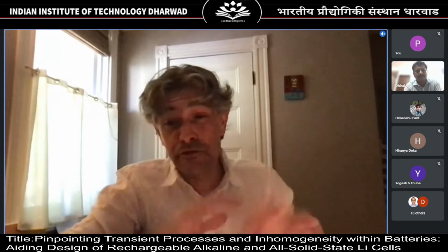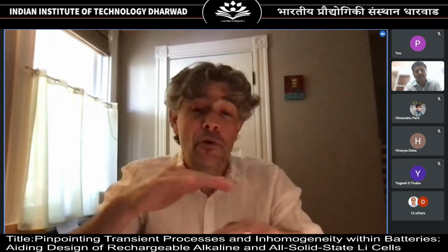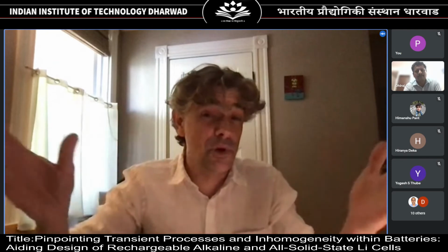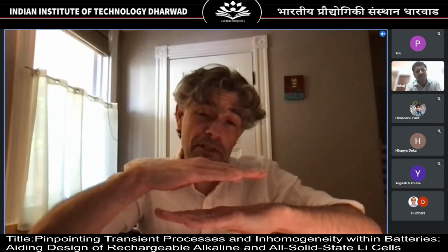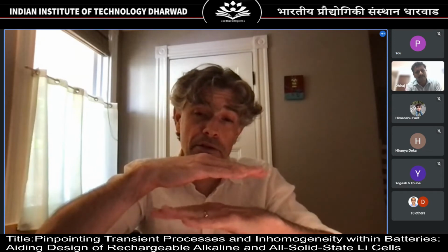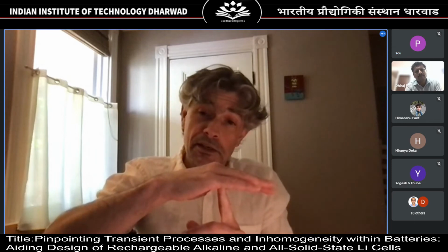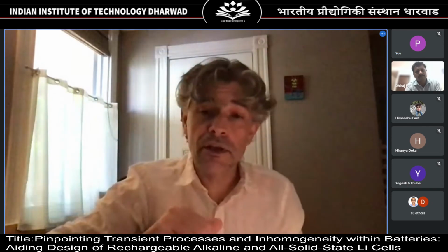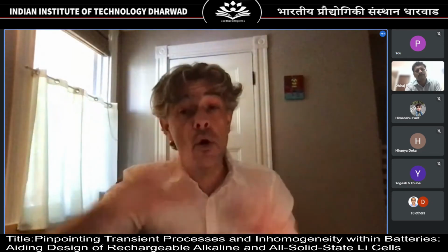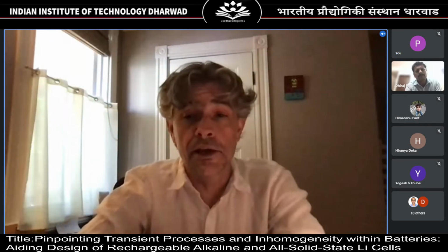Now, the layered form is even different because I showed that it maybe has those pillars in it. So that's one difference. How many pillars? Where are the pillars? You can think about where the pillars connect, right? So if there's an ion that's pillaring those layers, if that ion were to look up and down, would it see a manganese atom above and below it? Or would it see an oxygen atom above and below it? Or would it see a hole above and below it? So there are vacancies in these layers.